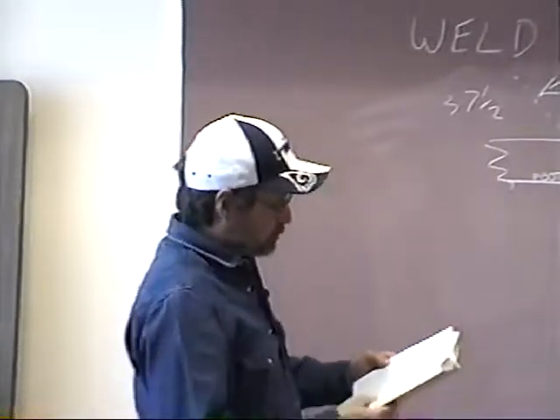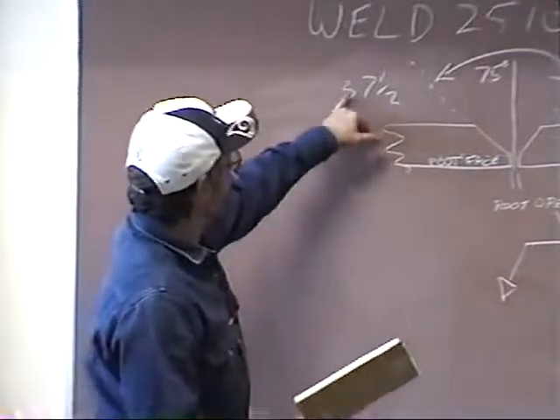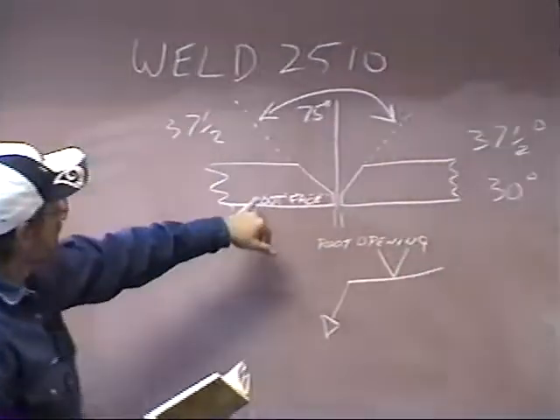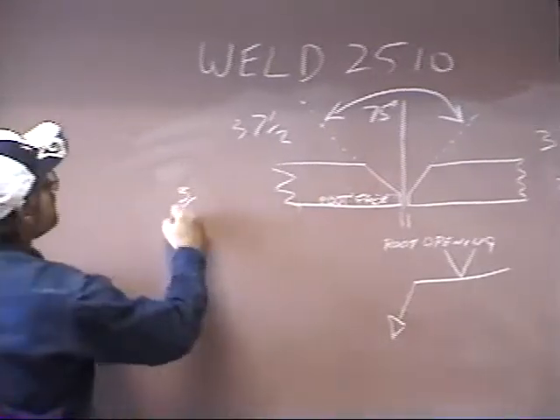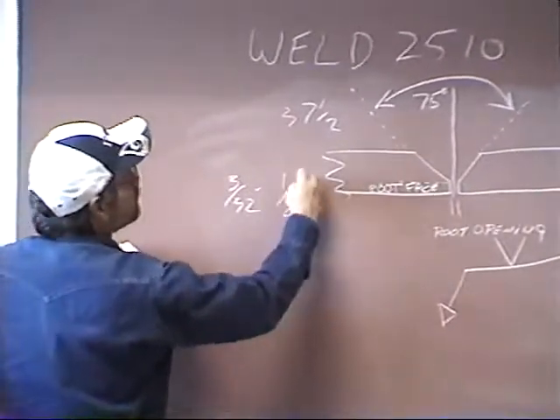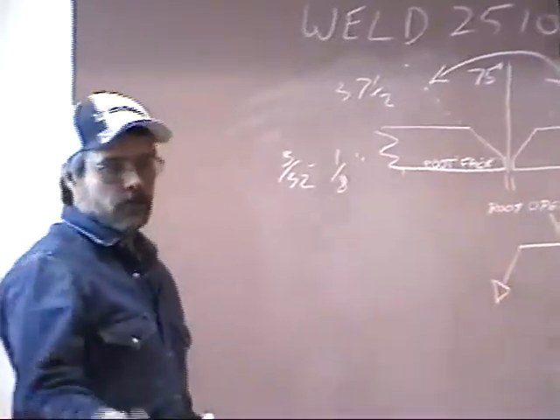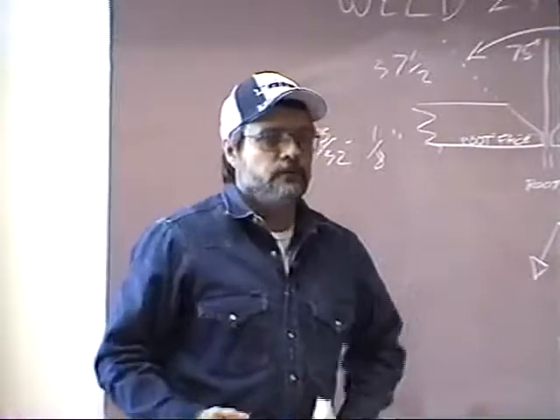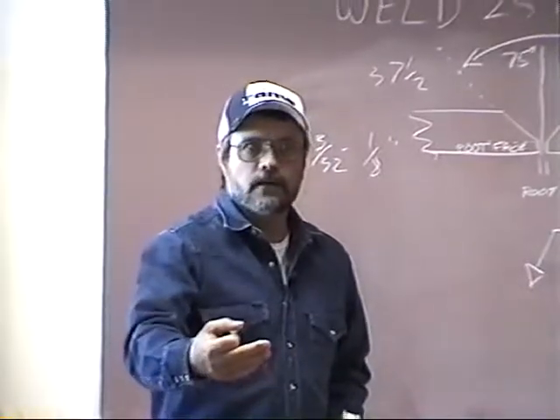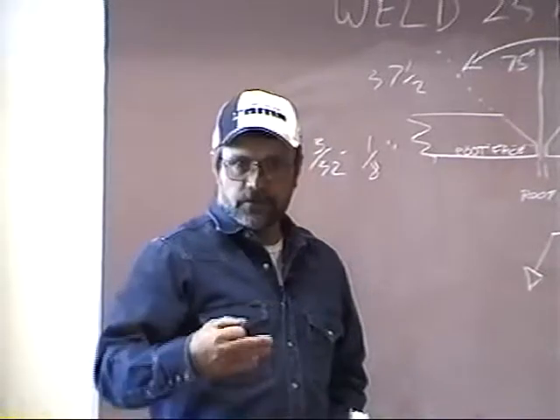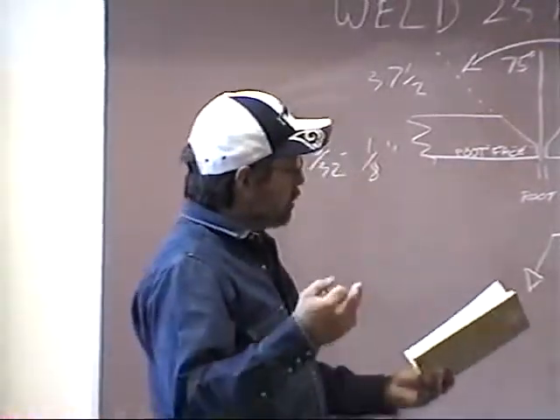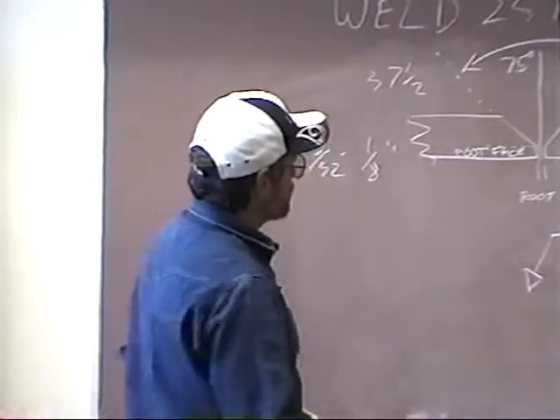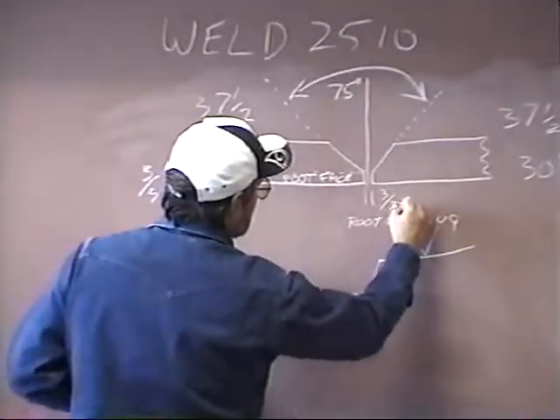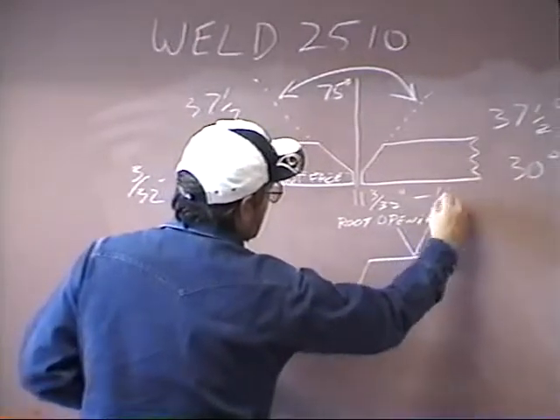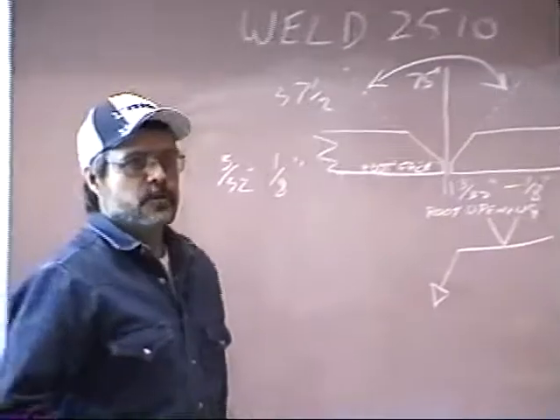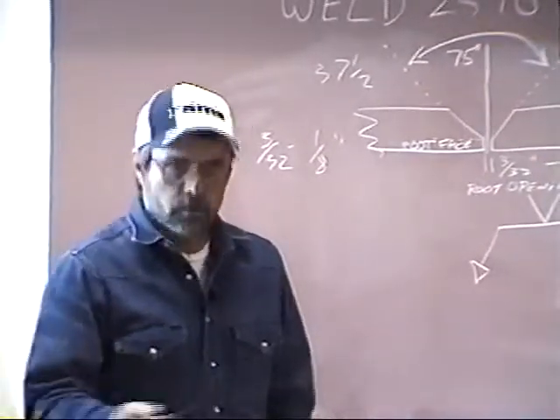Figure 4.2, they've given us some numbers. They've given us 37.5 and 75. Here they're saying 3/32 to 1/8 of an inch on your land. Of course, in pipe welding, if we're welding vertical up, we're teaching you to use a 1/8 inch land and a 3/32 root opening. But again, as I say, that can vary. And your welding procedure specification gives you room to move around.